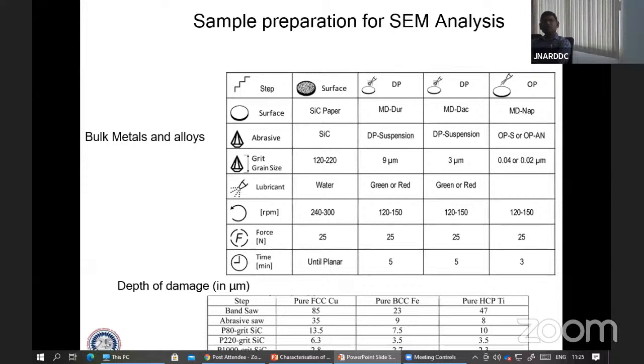And we also have to be very careful during the sample preparation. Suppose you are using a bandsaw and your material is copper, the depth of damage will be around 85 microns. And if you are using 220 grit size, then the depth of damage will be 6.3. So you have to be very careful during the polishing of these samples for SEM analysis, because it may damage your sample and then you may not get the original features in your sample. And also, suppose you are preparing an etchant, the chemical damage will also be involved. So you also have to take care of that to avoid any misleading features.